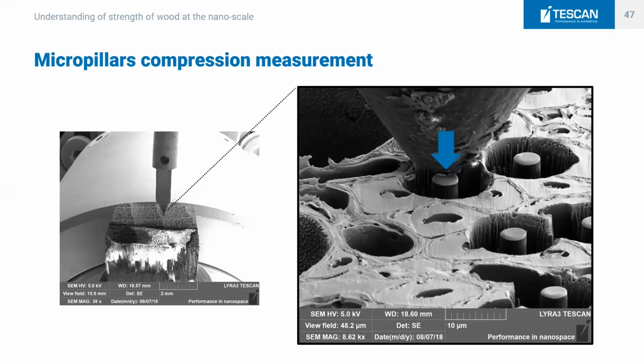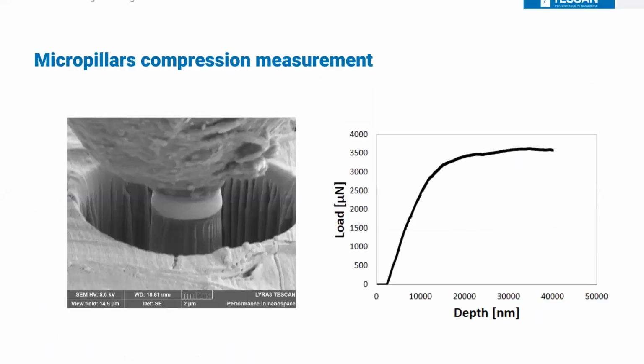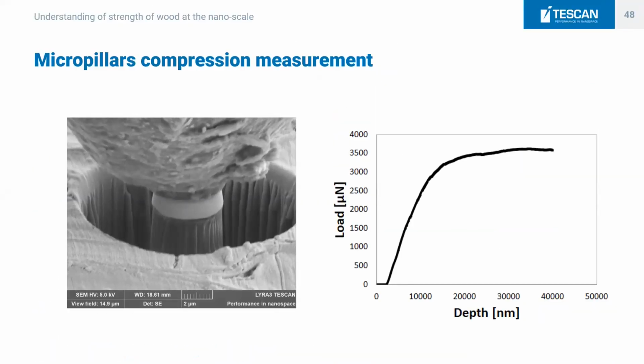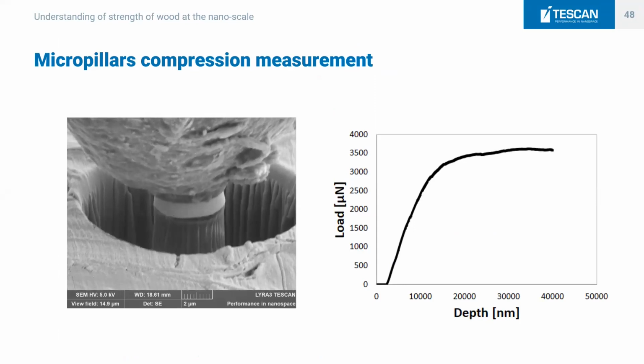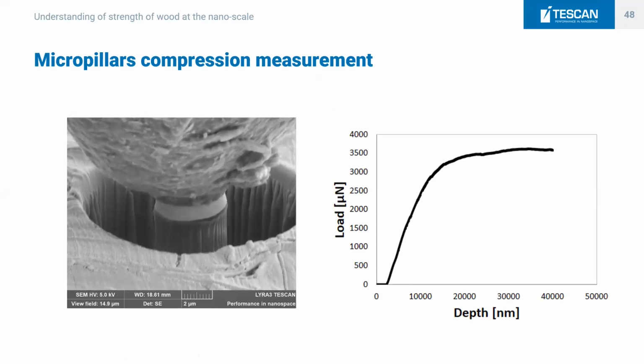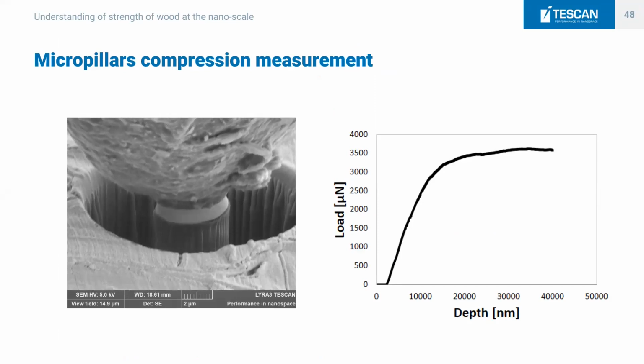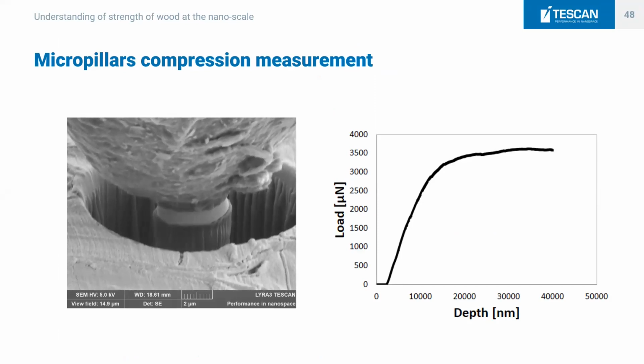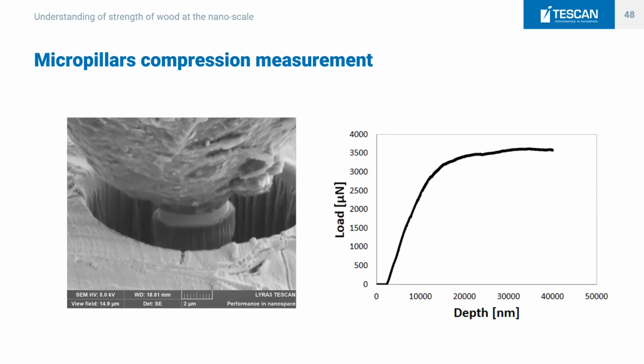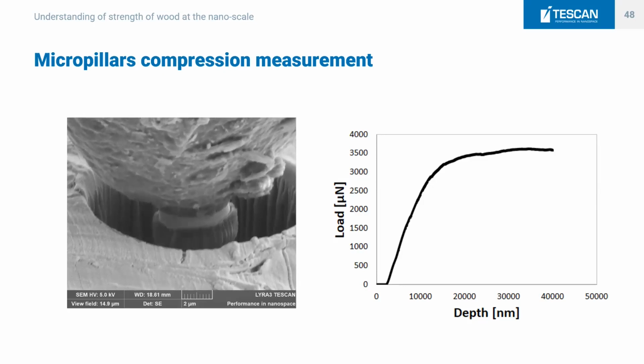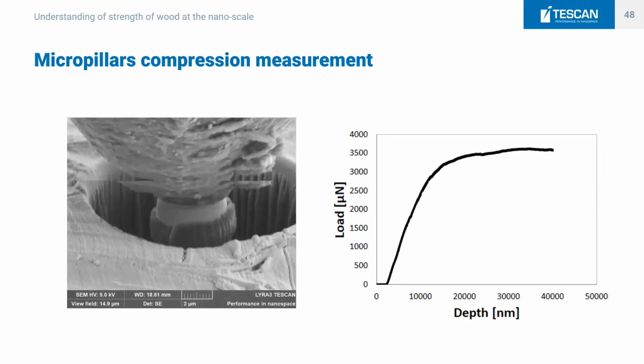And we put a nanoindenter with the compression head on. We focused on the micropillar, we compress them and basically make this micromechanical test. And you really get what you would expect from any mechanical test. So you get these graphs with load and depth, so displacements and load in micronewtons. And you can also observe the deformation of the micropillars. So this is how the test is done at the nanoscale until the failure.